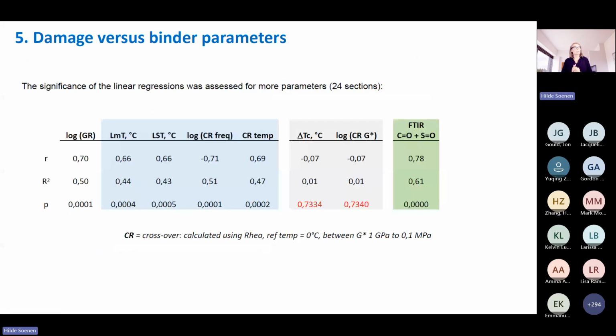We did the same thing for some more parameters, as you can see here. So using the limiting temperature, the limiting stiffness temperature, the crossover frequency and the crossover temperature, you see that they all have a very similar coefficient of determination, and they are significant. On the other hand, delta TC or the log crossover stiffness did not show a correlation. And finally, from FTIR, if we took the sum of carbonyls and sulfoxides, there we found the best correlation and also very significant.